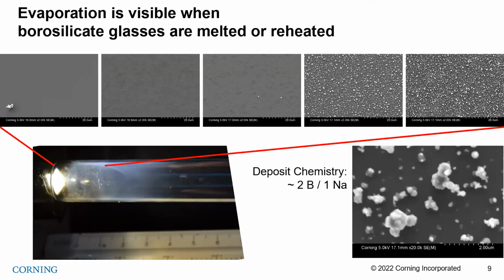And so we could image this with electron microscopy, and far away from the evaporating source on the right-hand side of the image here, you can see these deposits, these little spheres of sodium borate compound that have deposited during that forming process. On the left-hand side, you can see where it was heated and where that material evolved from. There's almost no evidence that occurred.